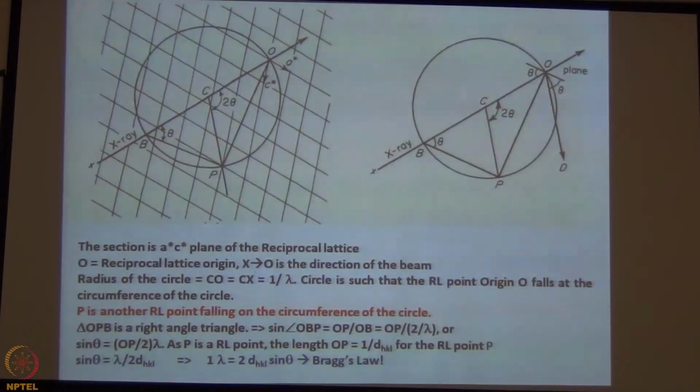If I rotate it, what I am going to rotate is this grid. If I rotate this grid, at some point this reciprocal lattice point which is inside will cross somewhere here, will cause diffraction. If something is here, at some point it will cross this region, and will cause diffraction in a different direction.